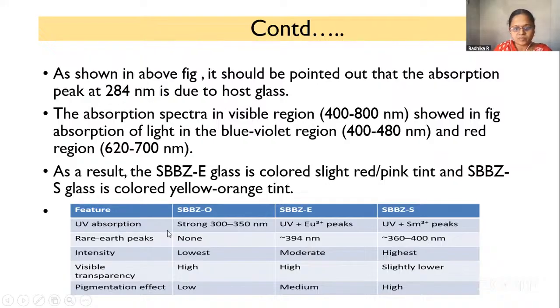UV absorption for undoped glass is in the range of 300 to 350, the europium doped glass is around 394 nanometers, and the samarium glass is around 360 to 400 nanometer range. And here the pigmentation effect shown by the undoped glass is very low, the europium doped glass is medium, and the samarium glass is high.